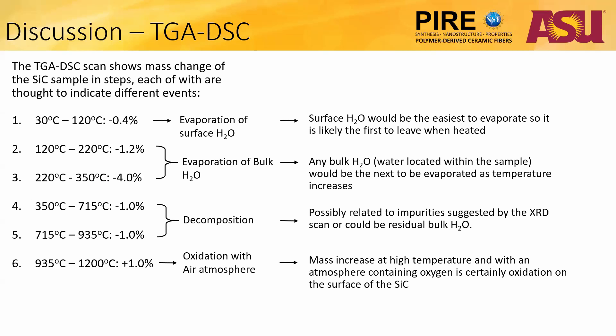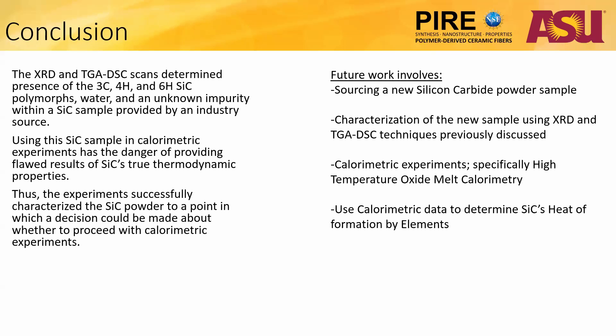In all, it is thought that roughly five to six percent of the sample mass is water from these results. The XRD and the TGA-DSC experiments were able to determine the presence of multiple SiC polymorphs, water, and an unknown impurity in the industrial-sourced SiC sample. Given that the impurity is still unidentified and has an unknown energy state, performing calorimetry on this sample would provide flawed results and give incorrect information about silicon carbide's thermodynamic properties.